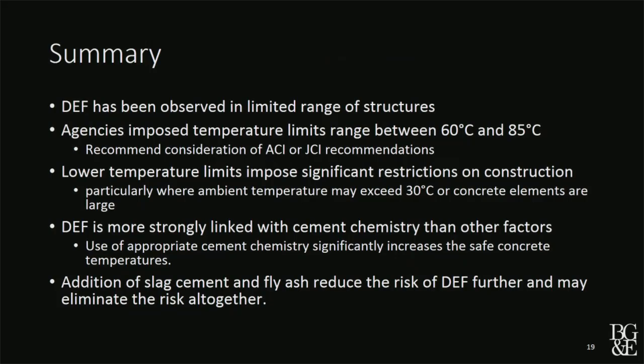So I want to conclude with delayed ettringite formation has been observed in a very limited number of structures, but I'm not going to discount those structures. Those structures that have DEF, it's a significant problem. So people have put limits, and those limits on temperature range anywhere between 60 and 85 degrees. And choosing those low limits may really restrict the use of concrete. It's more linked to the cement chemistry than the temperature itself. You can make cements that are immune to DEF at 90 degrees Celsius. Now, they might not be all that useful as a cement material. They may not set fast, they may not get strong, but you can do it. And the additions of pozzolans, slags, and fly ashes basically eliminate the risk of delayed ettringite formation.